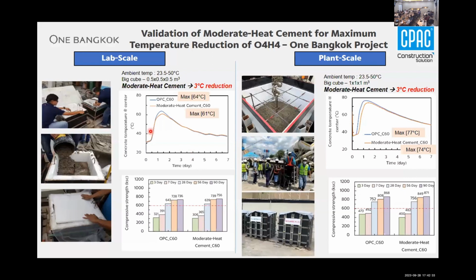So we did some adiabatic tests at lab scale, comparing OPC cement, ordinary Portland cement, and the moderate heat cement, and we found a temperature reduction of around 3 degrees Celsius. After that, we were quite happy about this one. Then we moved to plant scale. We cast a 1 cubic meter block and compared the temperature peak again. So we get the number again, 3 degrees Celsius, which is quite close to our lab test. So everyone is happy with this.